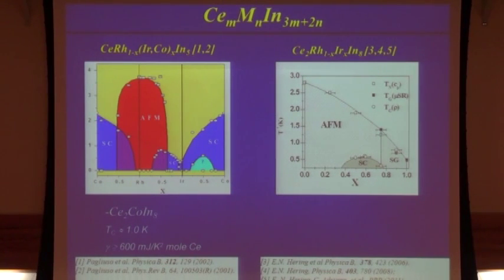So you have a very similar phase diagram, and if someone just looked at this, you could say, wow, that's amazing. That's kind of electron doping on one side and hole doping on the other, right? It looks like that. Of course not, because it's isovalent substitution here. There's no doping at all. And even though you have exactly the same shape, right? So what's going on? Well, we don't know. What's driving the magnetic state to superconductivity?